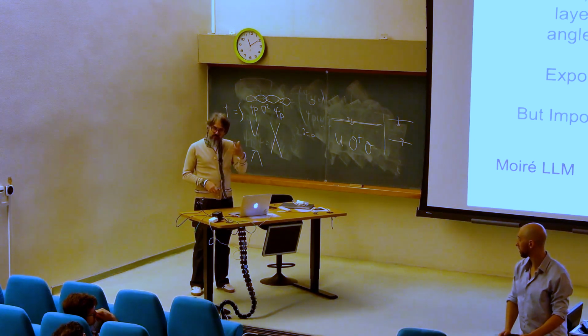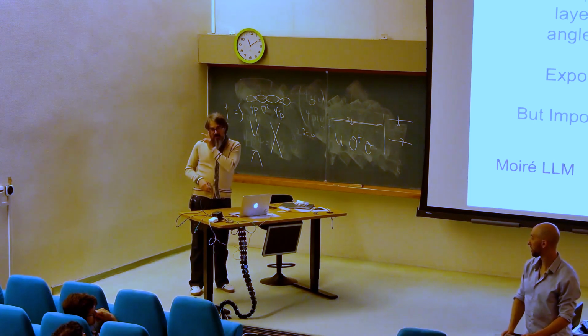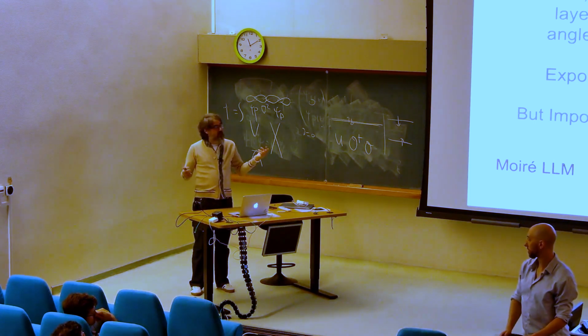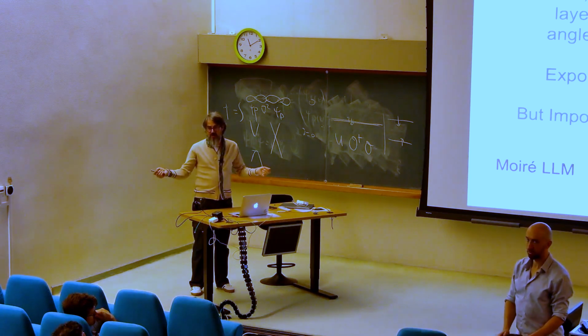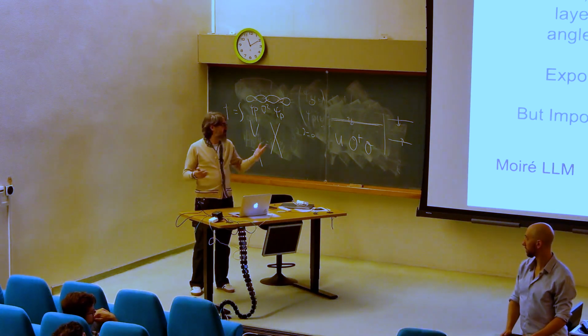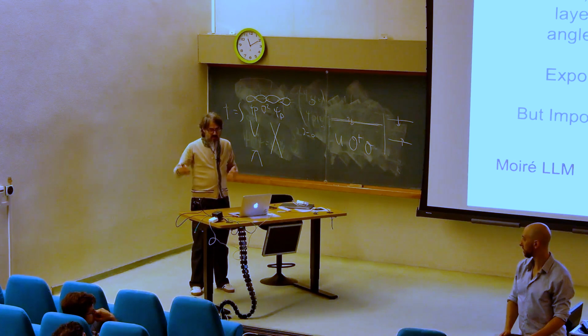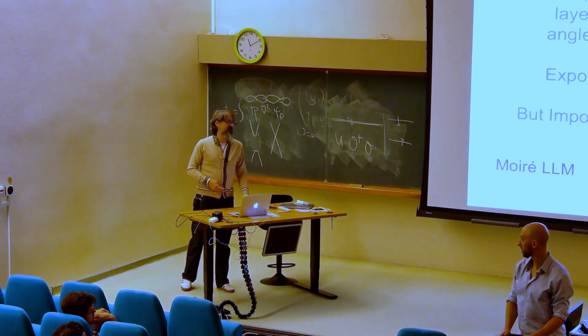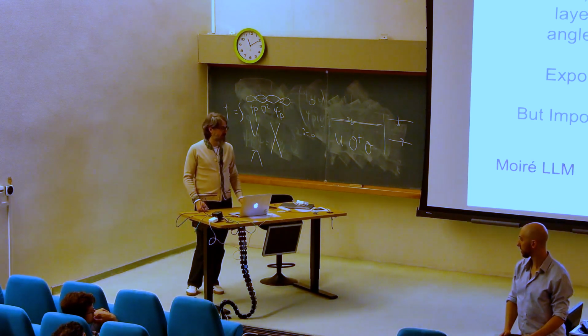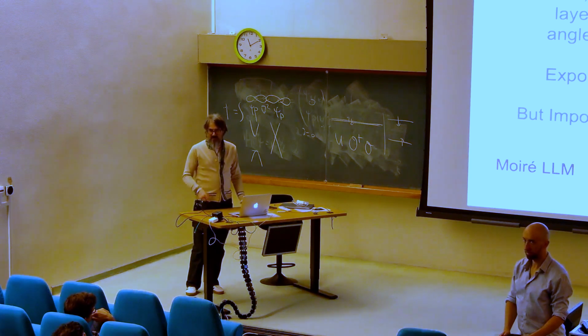periodic arrangement of them, first of all, it's a problem. If you don't get periodic arrangement, then you probably are going to get some localization. You need the mean free path. Part of the reason why this works is the mean free path is so large, much larger than the Moire cell. Otherwise, this Moire would act as a localization potential. But here, the mean free path of graphene is huge, much larger than the Moire unit cell. So I think potentially it could work. I never say never, obviously. I just don't know if you can reach the same level of cleanliness as in these samples.